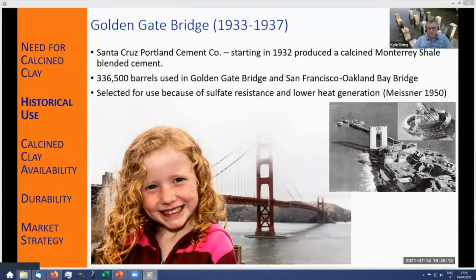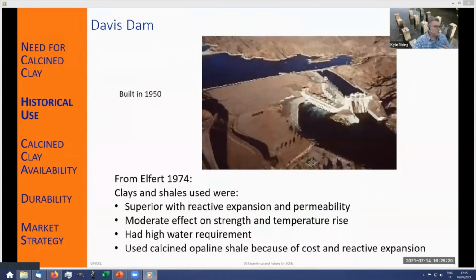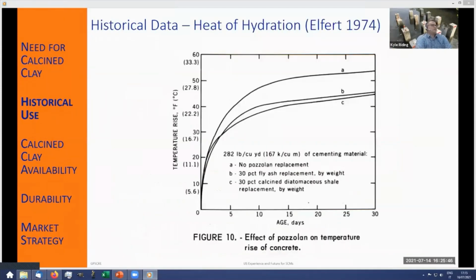So we can look to that past and see that it had very good performance. It was used in Davis Dam, and it was used also in the Bonneville Dam, and it was used cost effectively in those locations, and because it improved performance. In the Davis Dam, it did better with alkali silica reaction and water permeability. And so it had better performance than material with just Portland cement. So here's an example of hydration. So you can see that the use of calcined diatomaceous shale reduced the heat of hydration. It reduced thermal stresses and cracking in mass concrete dams, and was valued for that.